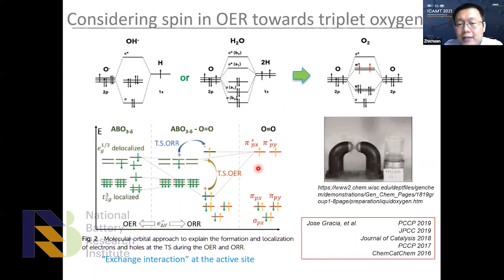So let's see how to understand it. For example, if we want to form a triplet oxygen bond, and we remove one spin-down electron, like the green colored area here, from the first oxygen, we have to remove another spin-down electron from the second oxygen. That means this is a spin-selected removal. Otherwise, we have to form a singlet oxygen, and in that case, thermodynamically, the reaction barrier will be increased. So this is pretty much like an exchange interaction at active sites.